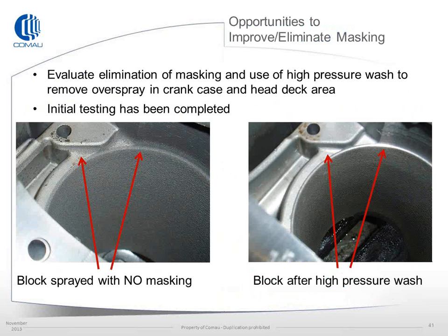In post-operation, after coating, if you're doing a non-selective prep, so where you've actually coated through the bore into the crankcase, we found that a high-pressure wash has the ability on die cast to easily remove it. On sand cast, it would be recommended to do a shadow mask with a small amount of jet washing. It definitely allows us to remove the coating throughout the bottom area without delaminating it into the bore.